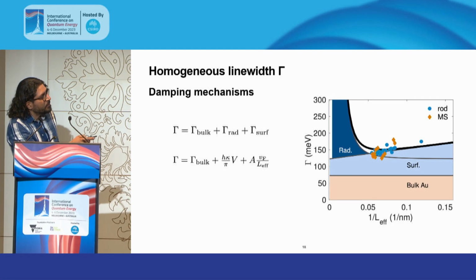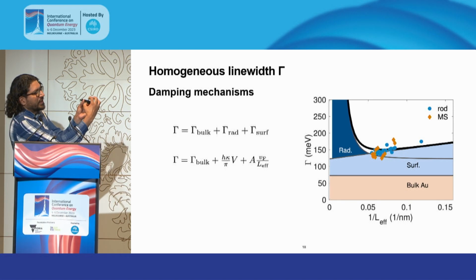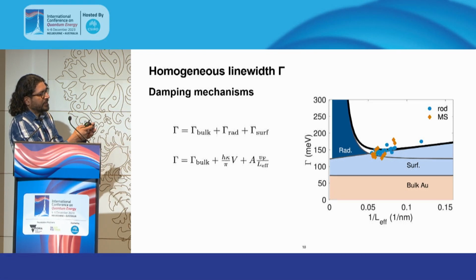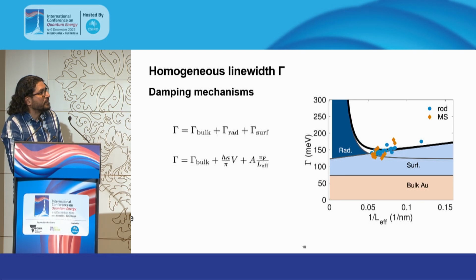As you can see here, most of our experimental data sit along the black line of the model, and there is not much difference between the rods and the rods with a bigger cap. The bigger cap is only changing the average distance of the electrons to the surface.